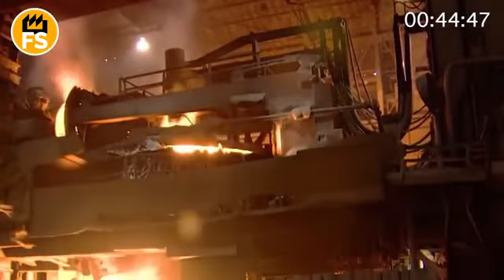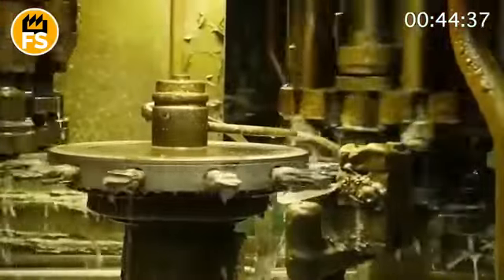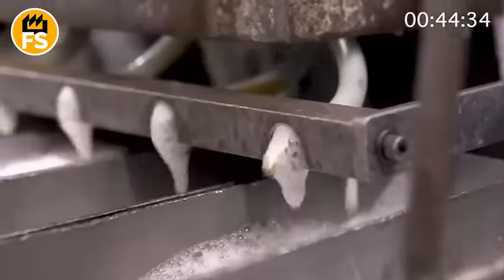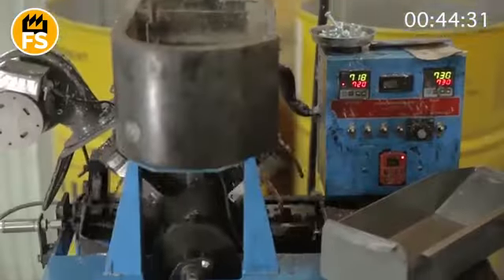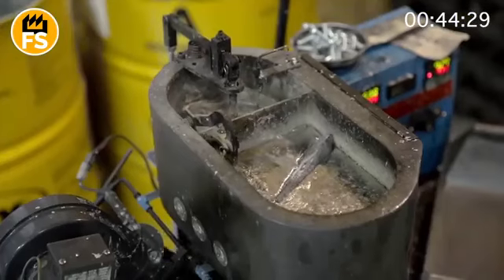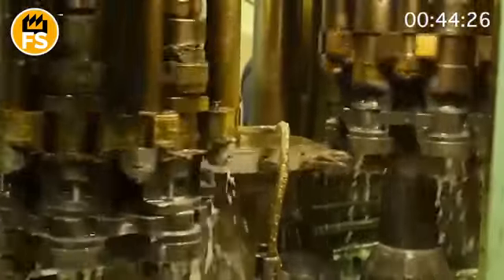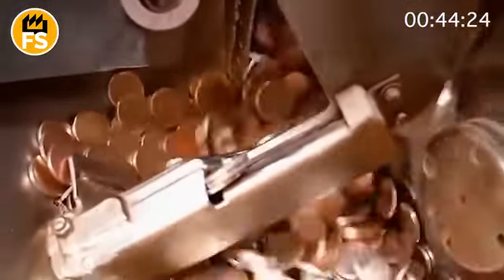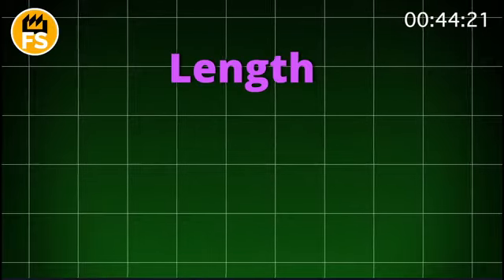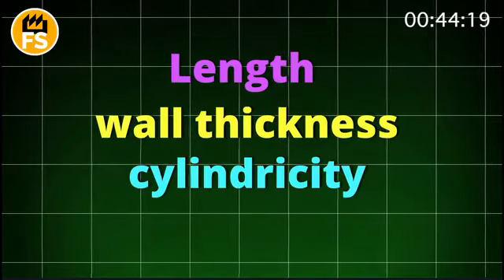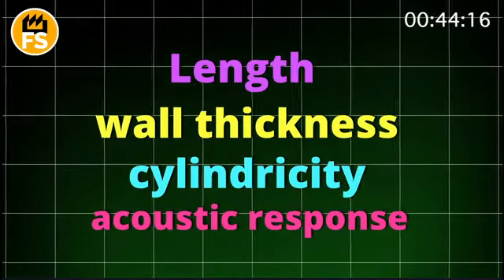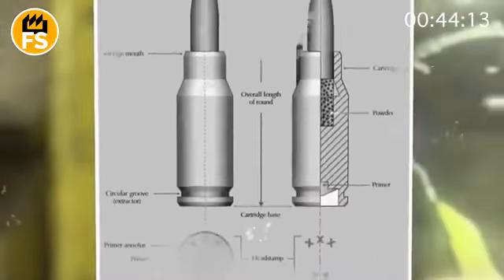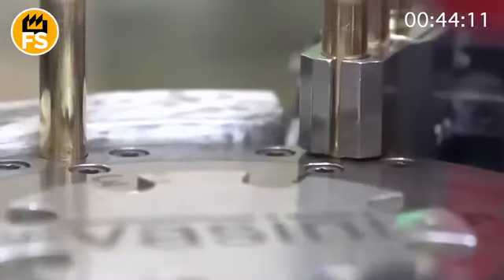Each casing is annealed after drawing. This involves heating it to 1000 degrees Fahrenheit to relieve internal stress in the metal. Otherwise, the casing could crack during firing. Then, it's cooled in water and cleaned in an acid solution to remove scale and lubricant. Next, calibration and weighing. The casings pass through a high-precision laser control system. A weight discrepancy means automatic rejection. Length, wall thickness, cylindricity, and even acoustic response are similarly checked. Special sensors detect if a casing has microcracks or internal defects.